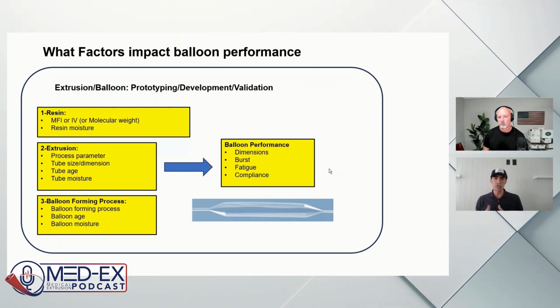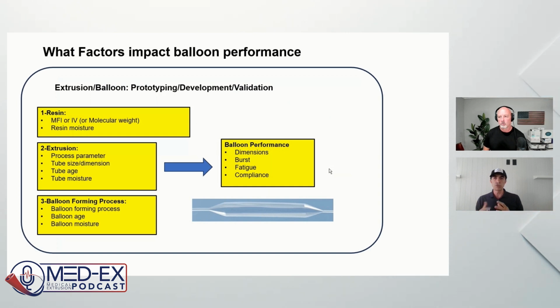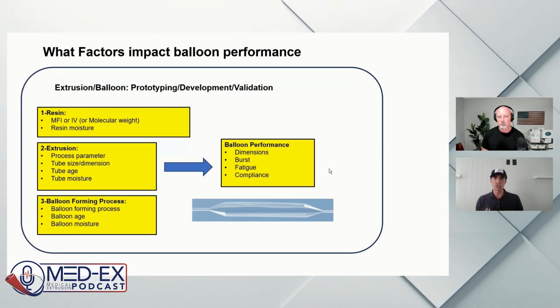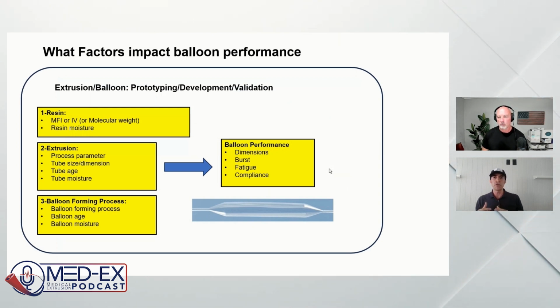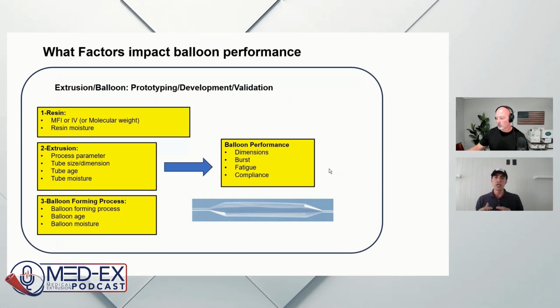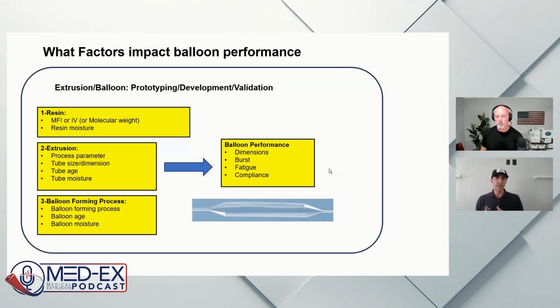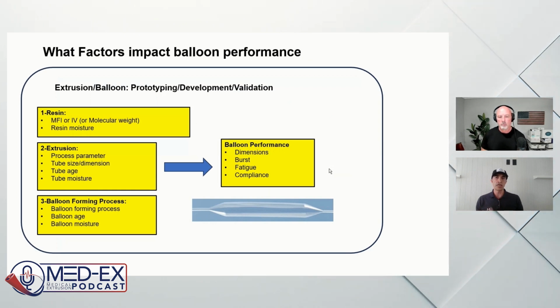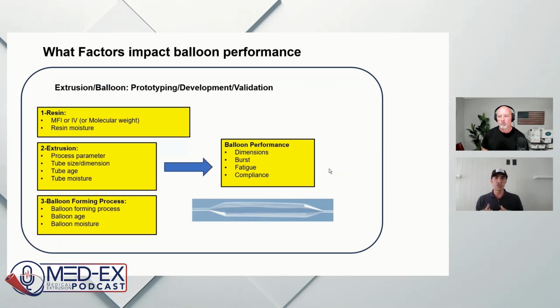Tube age is also important. We know that for some materials that have a glass transition around room temperature, over time, the properties of the material will change because of some movement in the molecular structure of the material. So they become a little bit stiffer, and the stretchability would change. So those are also parameters that you have to keep in mind. Tube moisture is also important. The same principle: moisture would act as a softening agent for polymers, and it could reduce the stiffness of the material, making it more stretchable.